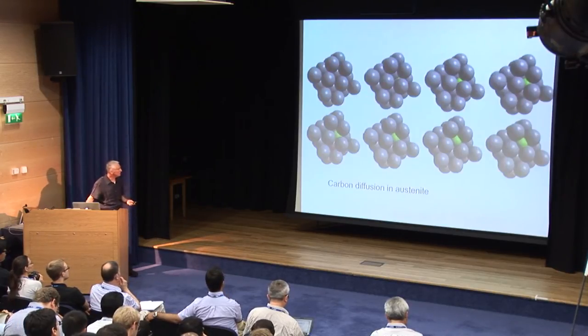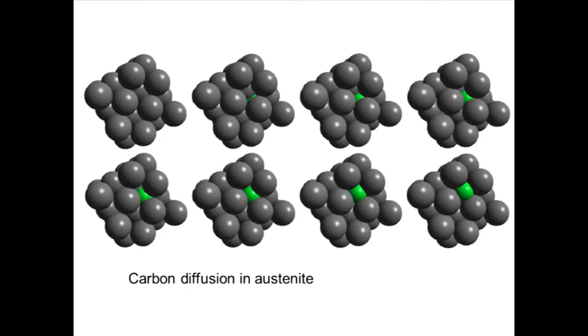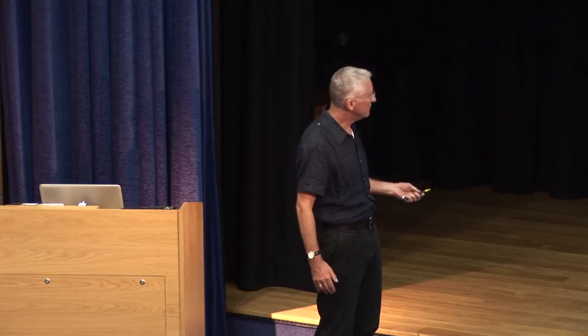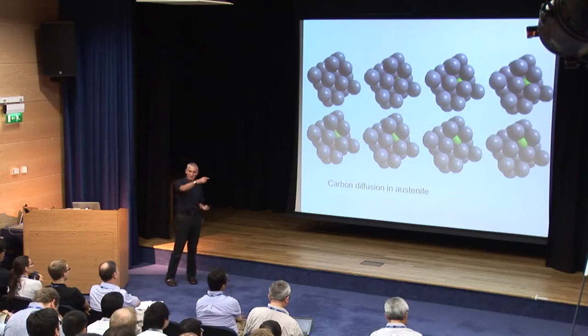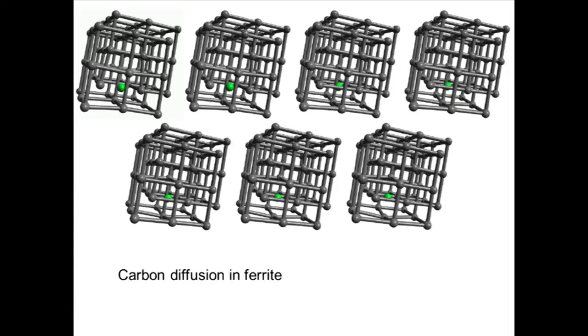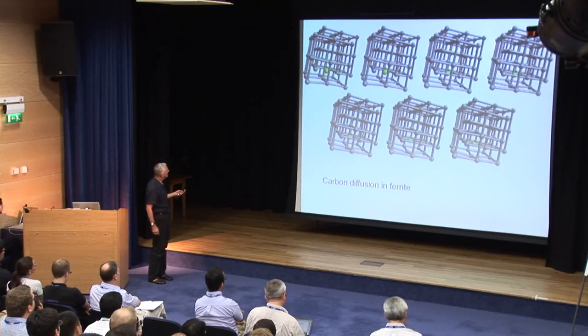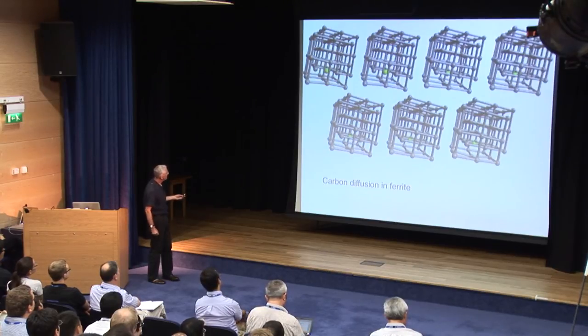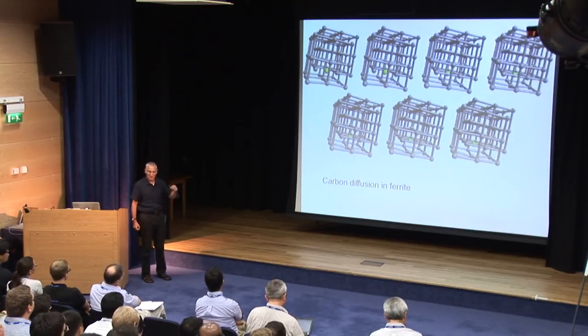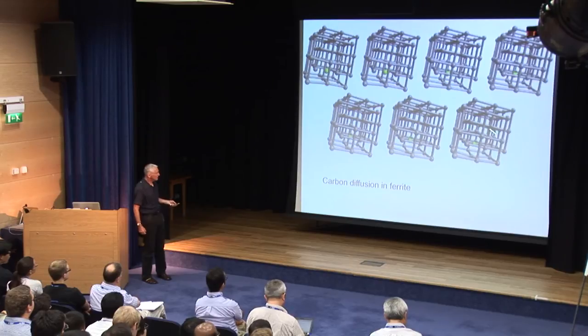Here are snapshots of carbon diffusing in austenite. The carbon atom pushes its way through — it's almost as if at the saddle point you have AAA stacking, which is always regarded as a heresy in metallurgy. The carbon doesn't hop first to a tetrahedral site and then on to the next octahedral site; it just forces its way straight through the nearest-neighbor bond between two iron atoms, which has a lower migration barrier. And here's the polaron moving — the physicist's way of thinking about a carbon atom in ferrite — where you get a large distortion because the octahedron is not regular in BCC. These two iron atoms are pushed aside in the [001] direction, and once the carbon has migrated, the distortion is now in the [001] direction — this is what I mean by reorienting the force dipole.